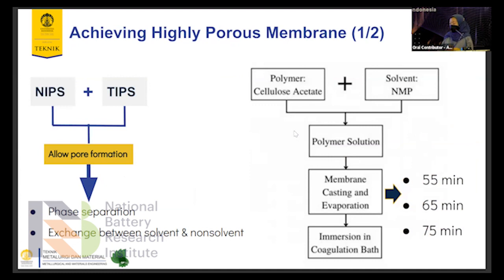The commercial separator has the other problem, which is low porosity and low wettability. So we need to overcome those problems by achieving a highly porous membrane. How? In this research, we recommend a method by combining NIPS and TIPS that will allow pore formation without adding any pore forming agent or additives. The NIPS and TIPS will induce a phase separation by combining the non-solvent induced phase separation and thermally induced phase separation. So there will be an exchange between the solvent and the non-solvent.